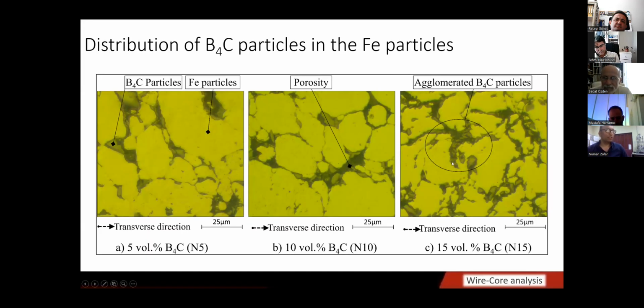The first question was, how is the distribution of B4C particles going to influence the microstructure? The answer is that at lower reinforcement ratios, you don't see agglomeration, but at higher reinforcement ratios, you see these B4C particles agglomerated at the interwire boundaries.